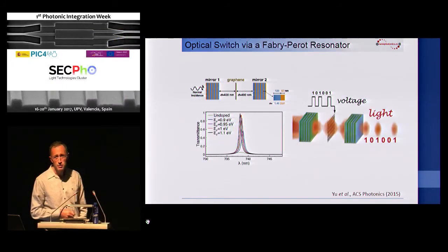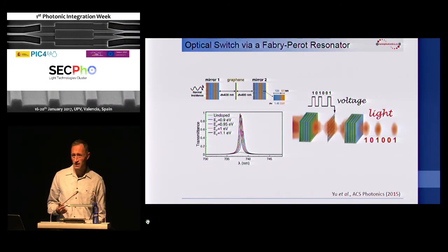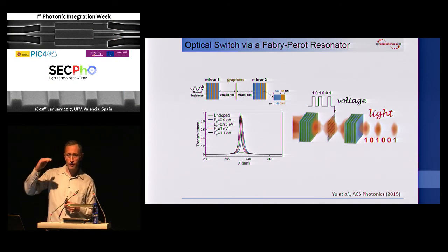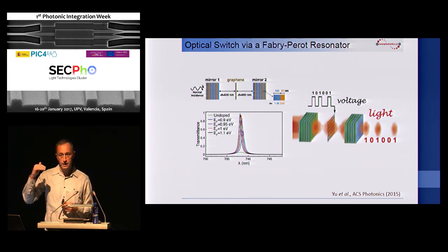And the idea is that essentially graphene is a very thin material, 1 atom thick. So you're talking about 0.3 nanometer. The absorption is not that high, it's 2.3%. But if you go to Pauli blocking, meaning you fill in enough electrons or holes so that you forbid the transition, then it becomes perfectly transparent, right?